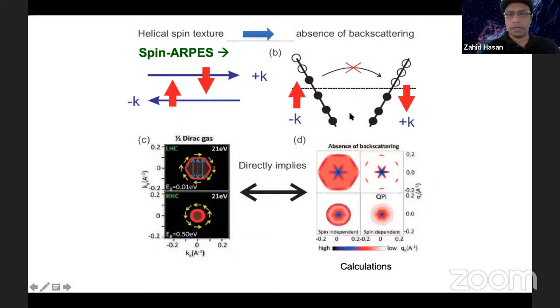You can also read it from here: an electron trying to take a U-turn has no available state unless you flip the spin. That means you have to have some sort of magnetic impurity or magnetic field breaking time reversal. So this is what is meant by topological insulators being protected by time reversal symmetry. As long as your time reversal symmetry is there, this backscattering is not allowed. So the absence of backscattering is a signature of a topological surface, or edge in two dimensions. This can also be directly seen by looking at the quasi-particle scattering using an STM, the quasi-particle interference pattern, where the backscattering is forbidden.